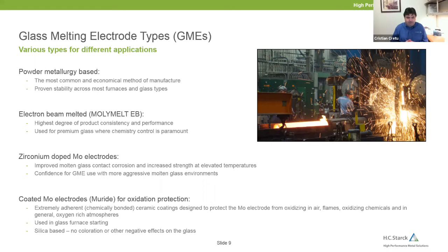Of course, molybdenum, although a strong metal, does have certain challenges, and where you really need to have improved strength and corrosion resistance at high temperatures, we offer zirconium doped electrodes to the market, right? There's a process in which a certain amount of zirconia is added, and zirconia acts as a stabilizer and a strengthening element to the molybdenum electrode, generating a premium electrode that is desirable in certain applications, as explained a little earlier.